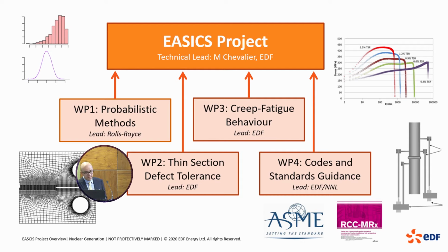So one thing, as I said, in the UK regulatory framework is we need to consider defect tolerance. So as soon as you have one boiler tube leak, or heat exchanger leak, then the regulator will have to say, well, now you've got a population of defects, how are you going to manage that? So heat exchangers are a safety critical part of the reactor, because obviously they take the heat out of the core, but actually you've got thousands of them in there, so an individual failure doesn't really cause a problem to the integrity of the overall system. But you have to manage that in terms of how can we prove that it's safe.